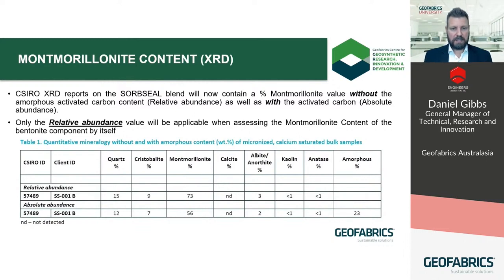powder as a whole and give you two results, an absolute abundance and a relative abundance. If you're simply interested in the montmorillonite content of the bentonite, then the value which is going to be reported will be the relative abundance value, as this will have had the activated carbon component subtracted.